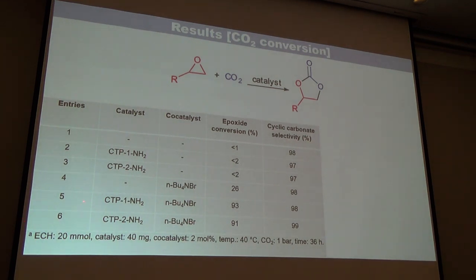Then we tested the catalyst performance in cyclic carbonate synthesis. Initially, the reaction performed without the catalyst shows a negligible epoxide conversion. In the presence of the CTP1 catalyst, it shows less than 2% conversion, and in the presence of CTP2, the conversion was nearly the same. When we tested the reaction in the presence of tetrabutylammonium bromide, the conversion was 26% with 98% product selectivity. When we test both together, the conversion drastically increases to 93% with a high product selectivity of 98%. CTP2 also shows quite similar performance, with 91% conversion and 99% product selectivity.